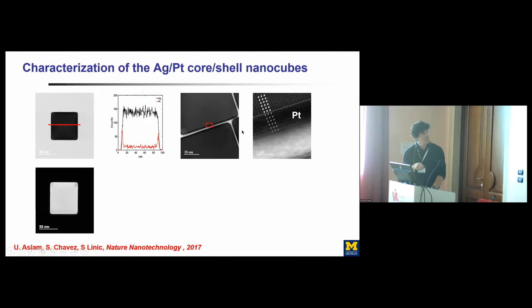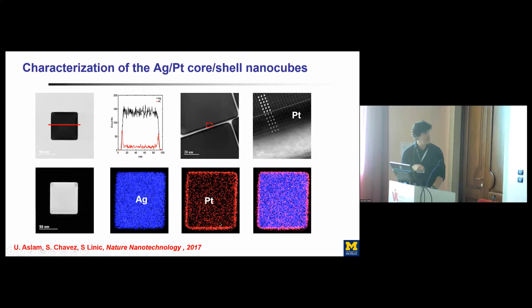You can also do some high resolution transmission electron microscopy. So this is now silver. In this particular case, you see platinum here. You have 1, 2, 3, 4, 5, 6 layers of platinum. Basically, you have a little bit over one, between 1 and 2 nanometers of platinum that's deposited on a core of silver that's about 60, 70 nanometers in size. And this is, again, some of the elemental mapping that we did for these silver platinum core shell nanoparticles.